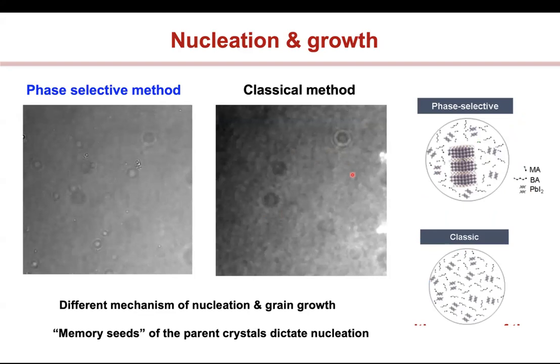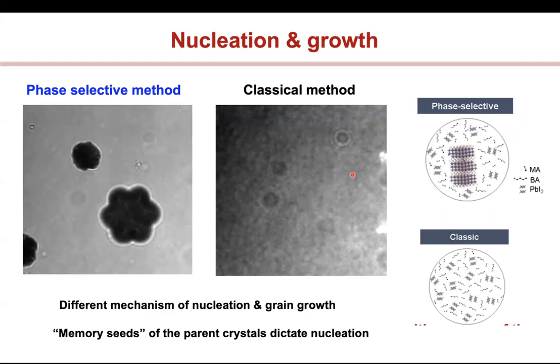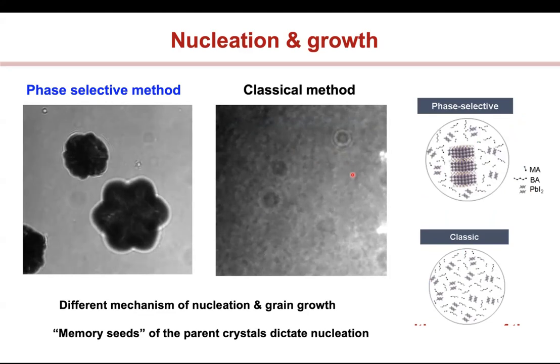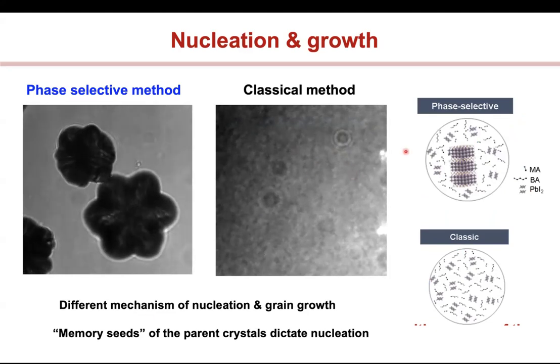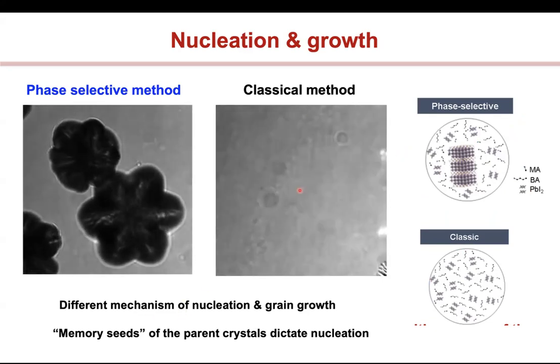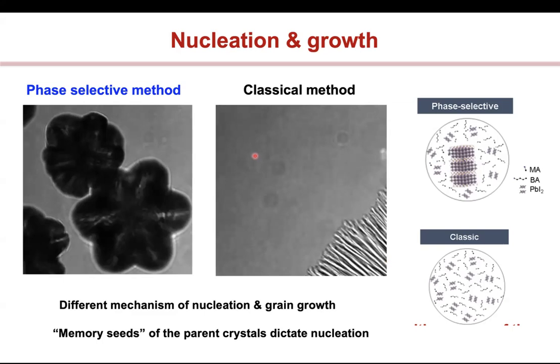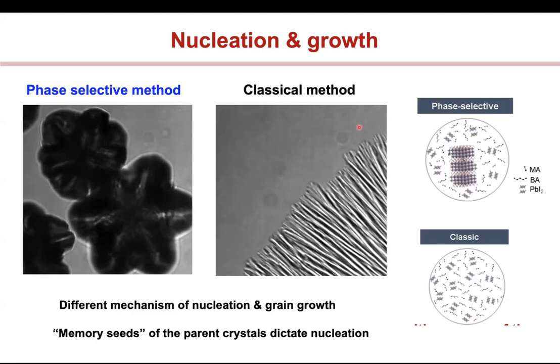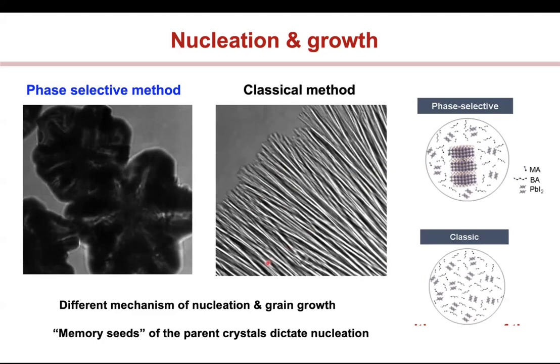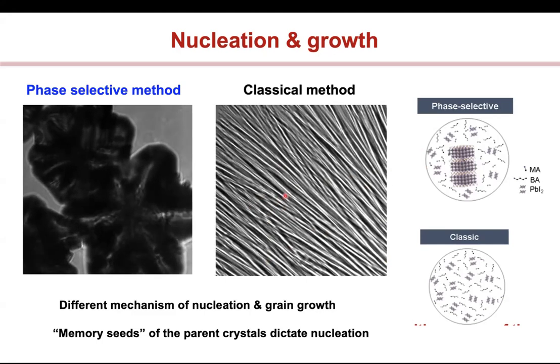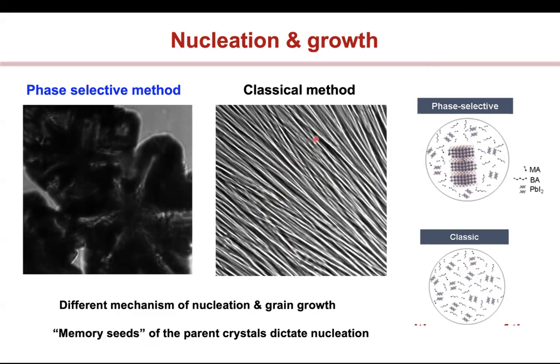You can actually see that in the phase selective method you get this very nice nucleation of the film. It's from a point source. These are all these seeds which are nucleating. Whereas if I compare this with the classical method, you see this very weird type of dendritic growth of the films, which gives you a lot of defects. And so these memory seeds then dictate the nucleation that you have.